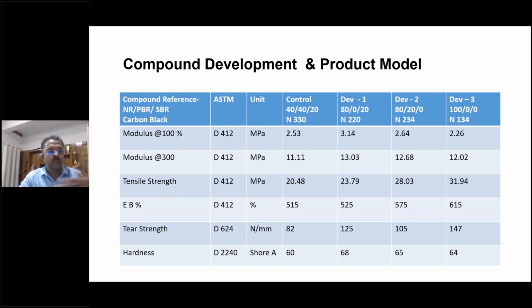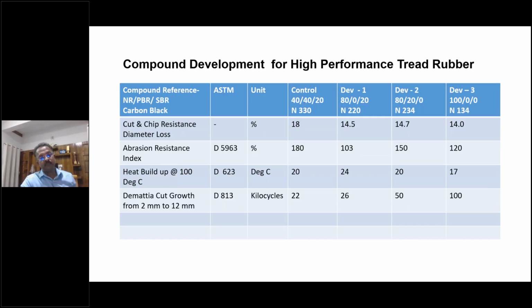So the properties: modulus 100%, modulus 300%, tensile strength, elongation, tear strength, hardness, then cut chip resistance. It's a very important property, cut chip resistance, the volume loss, abrasion index, ARI, heat buildup, and De Mattia cut growth resistance. This is a very, very critical parameter for tire performance. It has a very good correlation with tire performance, tire mileage.